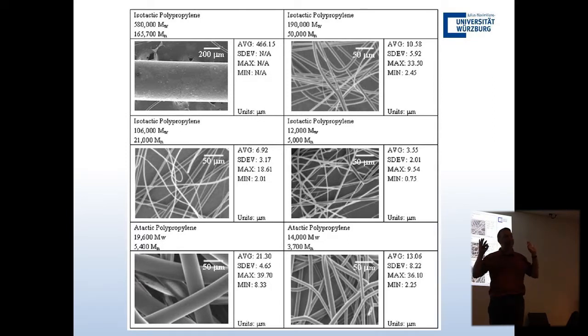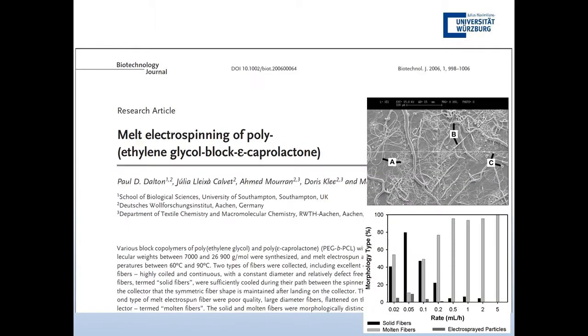And this paper literally stuck in the minds of everyone involved in electrospinning. Solution electrospinning, small fibers, melt electrospinning, large fibers. And that's the end of this, and that's basically the mindset within the electrospinning community through the 2000s. That even though there were papers later showing submicron fibers made with melt electrospinning, there was this general feeling that big fibers, melt electrospinning, bad, solution electrospinning, small fibers, like collagen, like ECM, good. And then it just kind of followed that path. I had a lot of conversations with people on this.